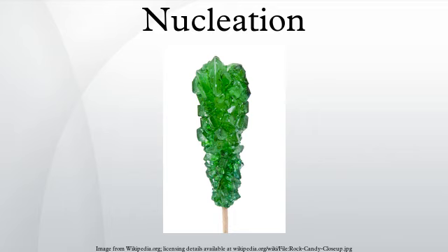Within the model this is assumed to be because, by chance, these droplets do not have even one impurity particle, and so there is no heterogeneous nucleation. Homogeneous nucleation is assumed to be negligible on the timescale of this experiment. The remaining droplets freeze in a stochastic way, at rate 0.02 per second if they have one impurity particle, 0.04 per second if they have two, and so on. This data is just one example, but it does illustrate common features of the nucleation of crystals in that there is clear evidence for heterogeneous nucleation, and that nucleation is clearly stochastic.